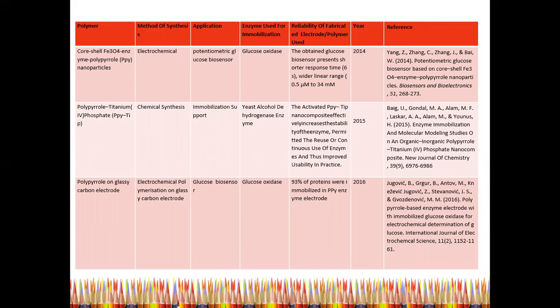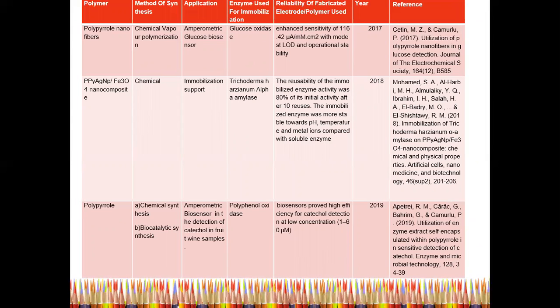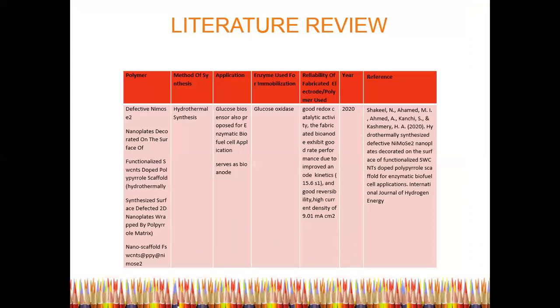In 2014, work showed that core-shell iron oxide enzyme polypyrrole nanoparticles were used as the platform for a potentiometric glucose biosensor, and the enzyme used for immobilization was glucose oxidase. Polypyrrole titanium 4-phosphate, prepared by chemical synthesis, was used in order to immobilize yeast alcohol dehydrogenase in the year 2015. And polypyrrole nanofibers, prepared by chemical vapor polymerization, were used to build an amperometric glucose biosensor. Now, polypyrrole has been both chemically and biocatalytically synthesized in order to immobilize polyphenol oxidase, and it has been successfully applied in an amperometric biosensor for the detection of catechol in fruit wine samples. Finally, in 2020, defective nickel molybdenum selenide nanoplates decorated on the surface of functionalized single-walled carbon nanotubes doped polypyrrole scaffold were also used in order to develop a glucose biosensor.